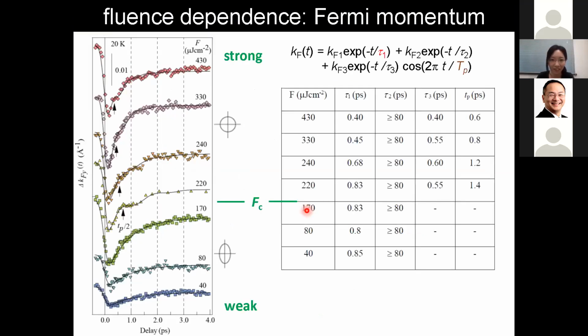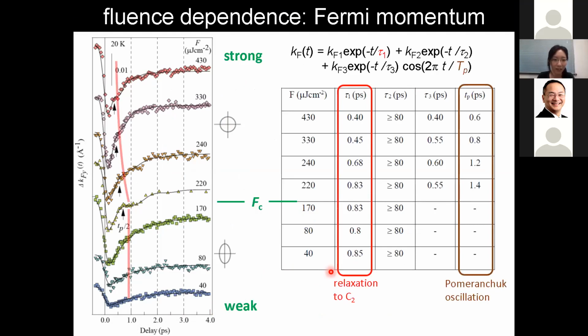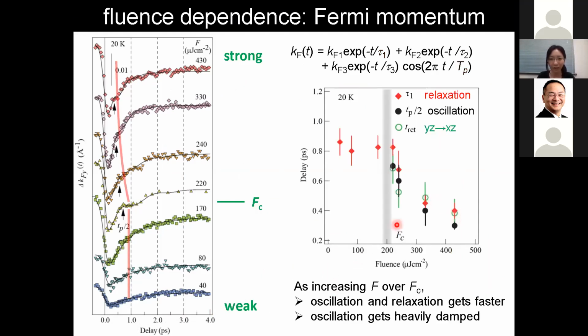Maybe I should skip the details here, but similar analysis can be done for each pump fluence. As a function of pump fluence, we get a very unusual behavior: when you go to the strongly excited regime, everything becomes faster. The oscillation becomes faster, and the relaxation time also becomes faster. So there's some kind of critical fluctuation appearing here.